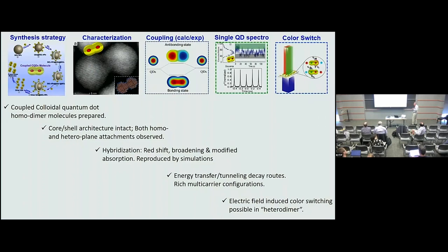The place where we did see an effect was when we went to zinc blende particles of cadmium selenide, cadmium sulfide, which are tetrahedral pyramids, tetrahedrons, and what we got was actually bow tie architectures. In the zinc blende, one of the ideas was, hey, this has only 111 facets, maybe we get 211 facets linking.